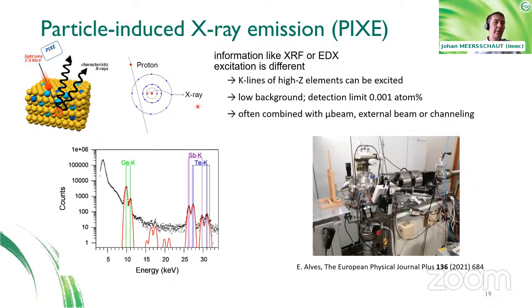This process of activation, in fact, is very likely. It's much more likely than the processes that we have seen so far. So the cross-section being very high, this is also a very sensitive technique. And many people will recognize this as being akin to X-ray fluorescence or, for example, energy dispersive X-ray spectrometry excited by electrons. The difference from the other techniques is that this is a very low background approach.